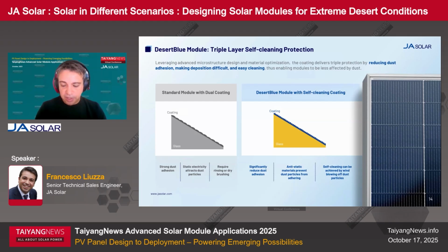From the animation, you can see how the particles adhere on the standard modules, and maybe the wind blowing effect is not sufficient to clean off the particles, and also rain is not frequent in the desert, of course, so it requires more cleaning operations on modules. The new DesertBlue glass offers this effect of reducing adhesion, and the wind blow can effectively blow the dust particles off the glass.